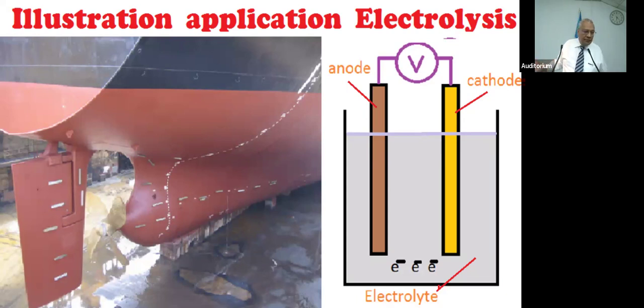So what you do is you take that steel to Lanka Transform galvanizing, and you get an 80 microns zinc layer. You are happy. Now you put it at the seaside. When the sea breeze comes and hits that, your electrolyte is introduced now. There is a fine moisture film. So you have the steel in the middle, the ferrous cathode here. You have a zinc layer around it, the anode here. And the salt moisture is the electrolyte here. And your metallic pathway is fully connected now.